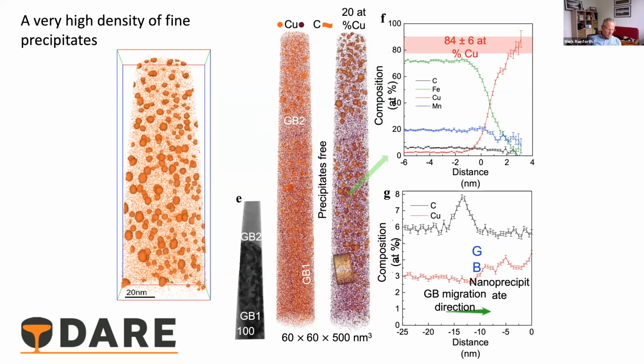Just to quantify that a bit more, there is the atom probe data from this material. On the left, you can see the atom probe tip, and you get an idea of the very high number density of copper precipitates there within the structure, as I say, that are perfectly coherent.